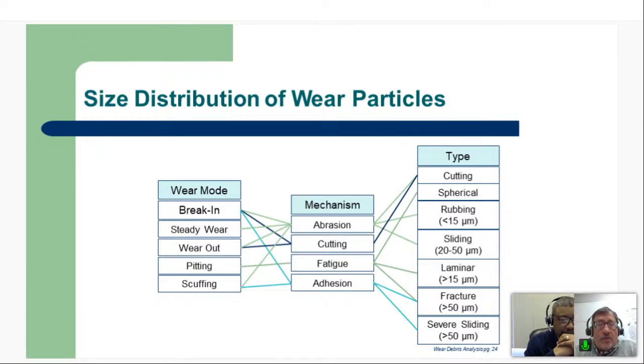And you can see you got different wear modes identified here: break-in wear, normal or steady wear, pitting, scuffing. Different mechanisms lead to that: abrasive wear mechanisms, cutting wear, fatigue and adhesion, and we lose lubricant films. And then we talk about the types of particles that they generate in terms of what we see under the microscope, what we take pictures of, and then we compare to libraries to say, this is what we have going on here. And we call these particles things like cutting wear particles and spherical particles, sliding wear, laminar, those types of things. And so we'll look at some examples here today.